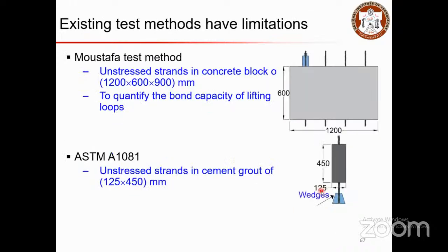It cannot be adapted. Researchers have worked on several methods to come up with a specific test methodology that can be used for pre-stressed concrete. The Moustafa test method uses a complete concrete block in which strands are embedded, and then a jack is placed to pull out the strand. But the disadvantage here is that the strands are not pre-stressed.